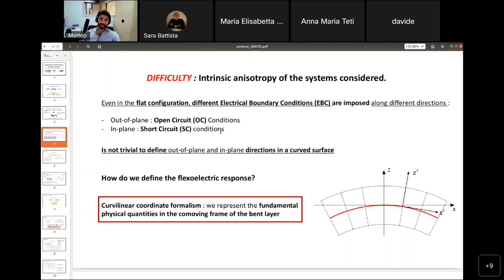But because of the reduced dimensionality of the system, there are some problems that we have to try to solve. Indeed, as I mentioned, because of the reduced dimensionality, that is, the fact that the system is defined as a finite system along the out-of-plane direction, we have an intrinsic anisotropy describing the system itself. This means that all the physical quantities that we consider, referring to different directions, are by definition different. That means that, for example, even in the flat configuration, the in-plane and out-of-plane responses have to be defined, for example, by use of different electric boundary conditions. For example, the in-plane response is usually defined by use of the so-called short-circuit conditions, while the out-of-plane one is defined by use of the open-circuit condition.